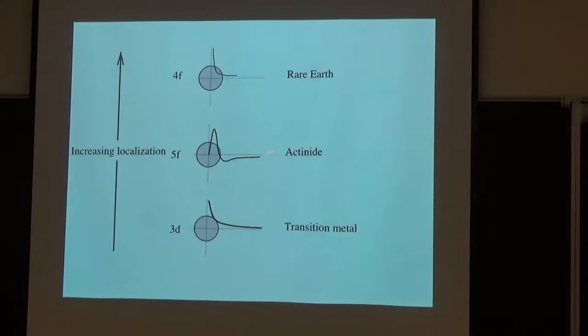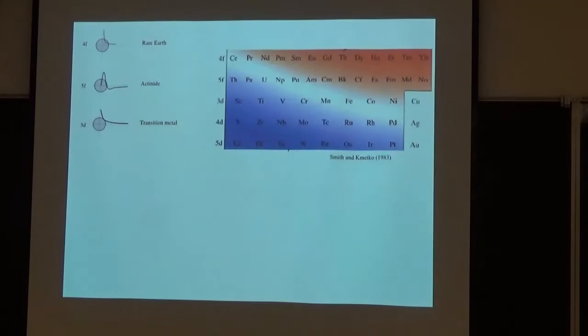And so these are even more localized than transition metals. In between them are the actinide 5Fs. And so it makes sense to reorganize the central rows of the periodic table in this order. This was first done by Kmetko and Smith in 1983. They reorganized it this way around. You can see there's a squeezing factor needed here because L equals 2 for the D electrons, so there's 10 electrons you can put into the D shell, whereas L equals 3 for the F electron, so that's 14 that you can put in here.